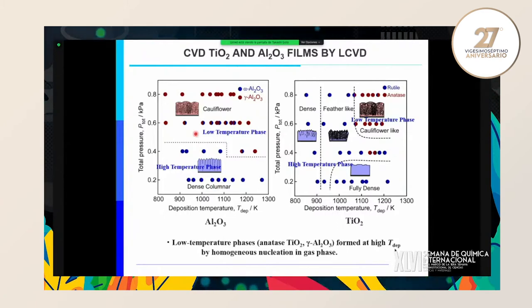And this situation is the same in the case of titanium oxide. The low temperature form, anatase, forms at high temperature, and the high temperature form, rutile, forms at low temperature. This is also caused by nucleation in the gas phase.